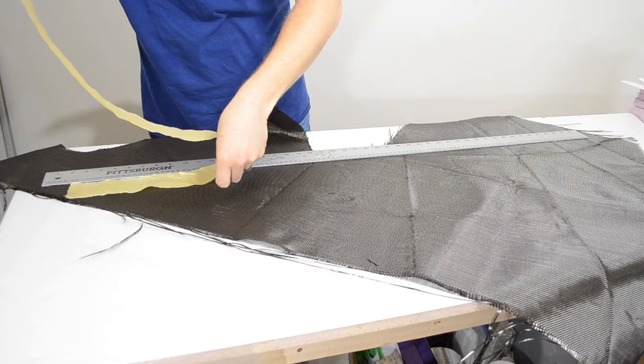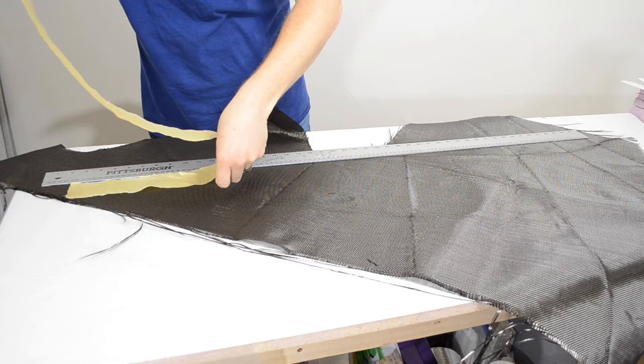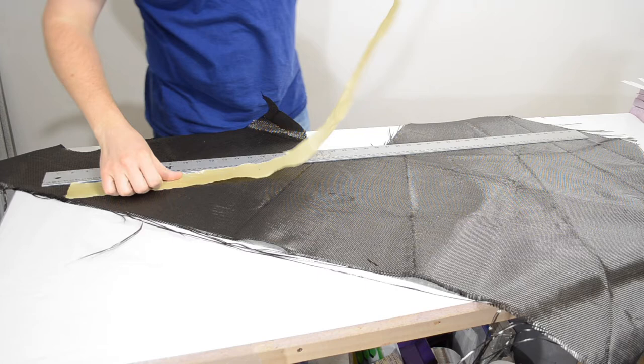With that done, I sprayed a generous coat of 3M77 onto the Kevlar, and I used a ruler to help me line it up as I pressed it down onto the carbon fabric. Make sure this is on a 45 degree bias. If your fabric is cut 0-90, you will never get it around the curves.